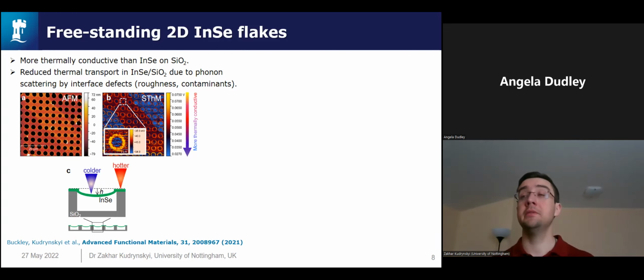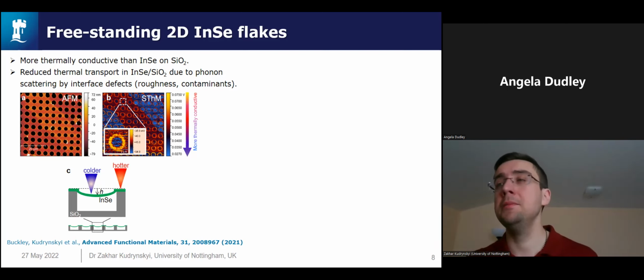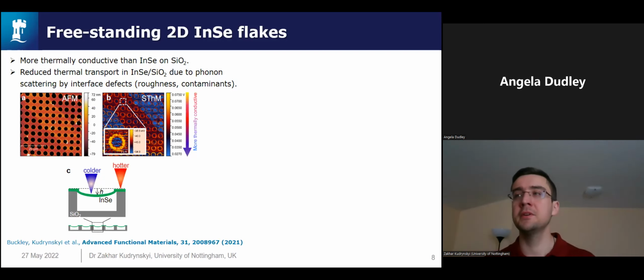Here we transferred indium selenide flakes on microwells in silicon dioxide. An AFM image here shows a flake that is partially freestanding and partially supported by the substrate. And here we have a thermal image of the same area. We can see that when the SThM probe is over the freestanding region, it is cooler. This actually means that indium selenide disperses heat here better than indium selenide on silicon dioxide. The reduced heat transport in the substrate-supported indium selenide is attributed to phonon scattering by interface defects caused by surface roughness and contamination.